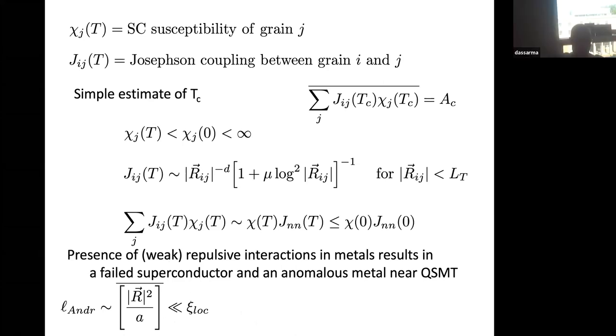So this brings up my last but reasonably important question. The superconductivity here may not be phonon mediated at all. I mean, experimentally, you do not know. Yes, but what's your inkling that the superconductivity that we're seeing in these anomalous metal superconductor transitions is probably- No, I think there's no doubt that it's phonon. I mean, it's aluminum on indium arsenide heterostructures. What do you think the mechanism of superconductivity in aluminum is? Standard phonon mediated. And similarly in molybdenum germanium. I don't know, maybe lanthanum aluminate strontium titanate might have an unconventional mechanism. If I had to bet, I would bet on phonons, but I don't think it's been established.